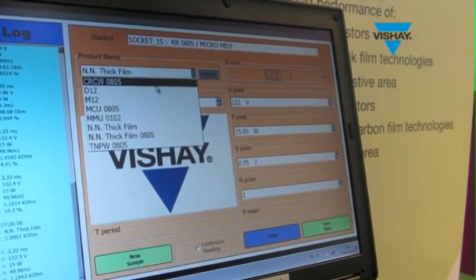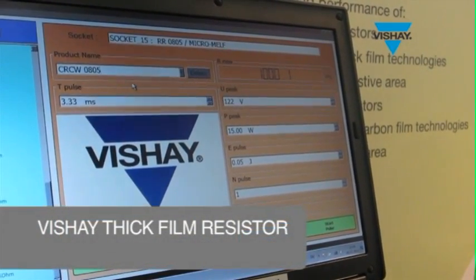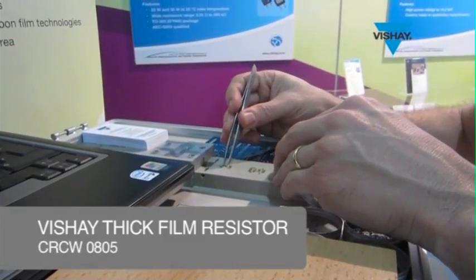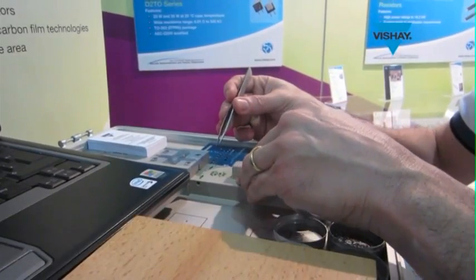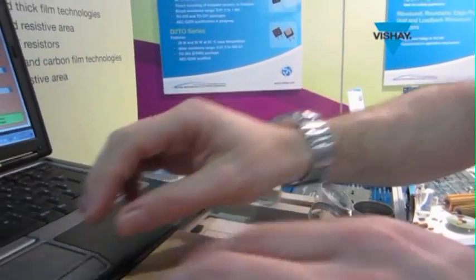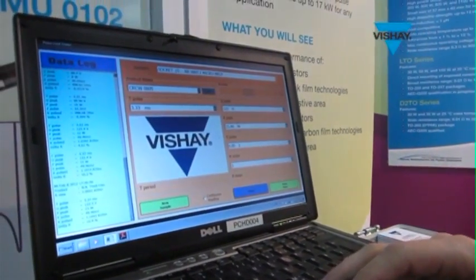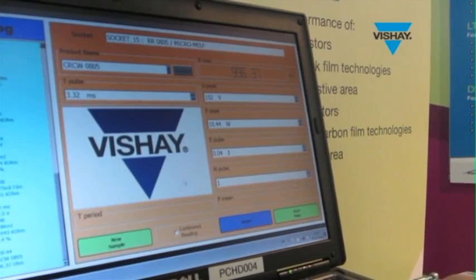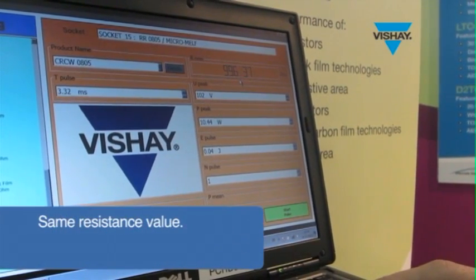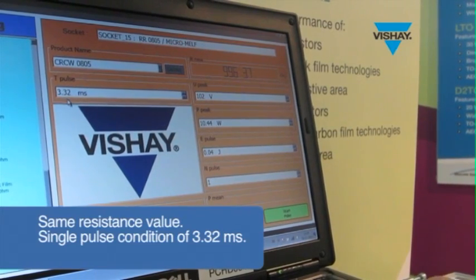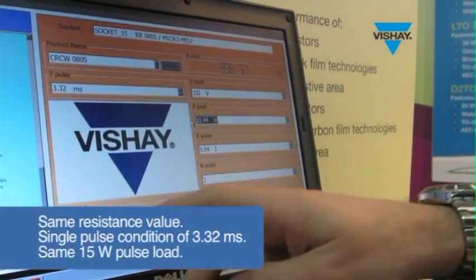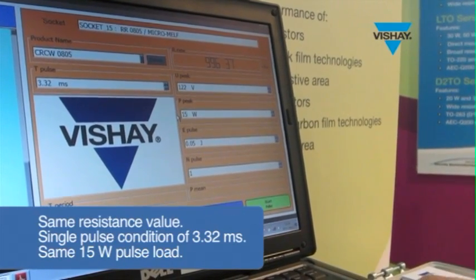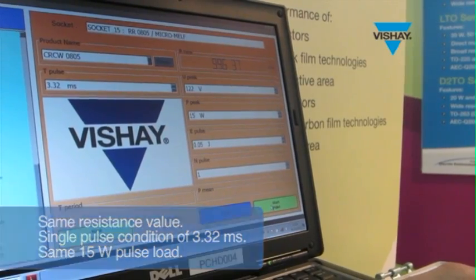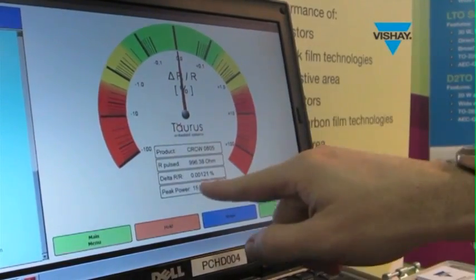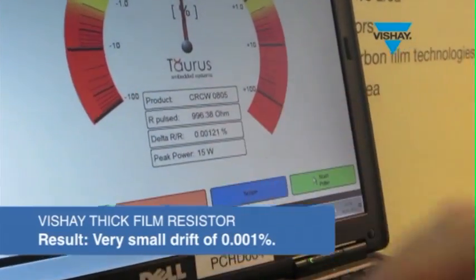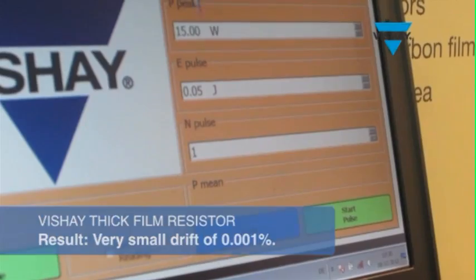Let's now switch to the Vishay thick film resistor, the CRCW 0805. They have similar solder pads and similar technology, but the Vishay components are using better materials, and so they will have better performance. So you can see that the resistance value is the same. It is again a single pulse condition of 3.3 milliseconds. And now let's start applying 15 watts, which was the last pulse load for the competitor part. And for the Vishay CRCW, you can see almost nothing happens in the component, only 0.001% of drift.